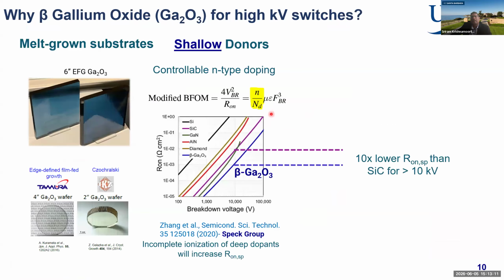And the other important aspect in a power switch is the fact that you need to have shallow dopants. So shallow doping is very important. When I say shallow doping, what I refer to is that the energy level of the dopant below the conduction band is comparable to thermal energy. And that is the case for gallium oxide. For gallium oxide, we can get dopants which are just a kT below the conduction band, and so you get close to 100% ionization efficiency at room temperature for these dopants.